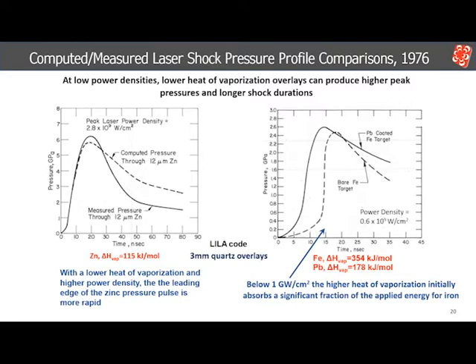In the figure on the right, the computed pressure profiles of iron and lead overlays were modeled with a lower power density. We saw earlier that lead outperformed iron in the etch pitting experiments at a low power density. For an input triangular pulse, like that shown in the previous slide, the two metals show quite different pressure profiles. The rise in pressure on iron occurs much further into the laser pulse than it does on lead. This can be attributed to iron requiring much more of the laser pulse's energy at the front end to generate enough vapor to increase the pressure. This results in a much shorter pressure pulse on iron than lead, even though the peak pressure is about the same.